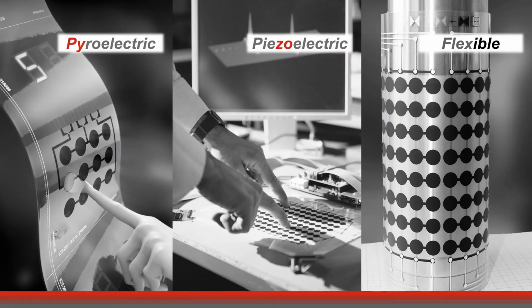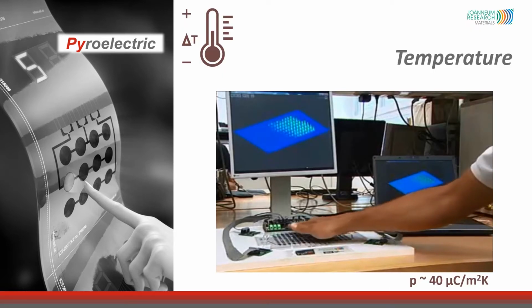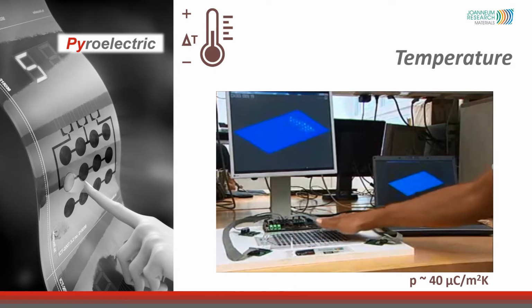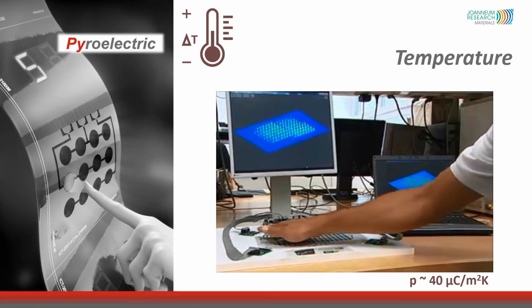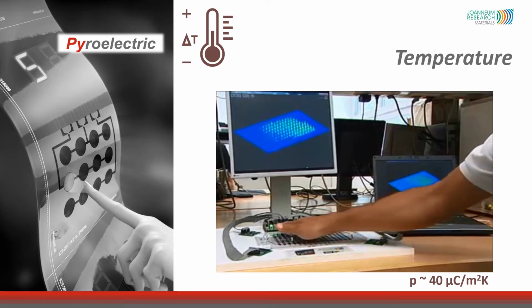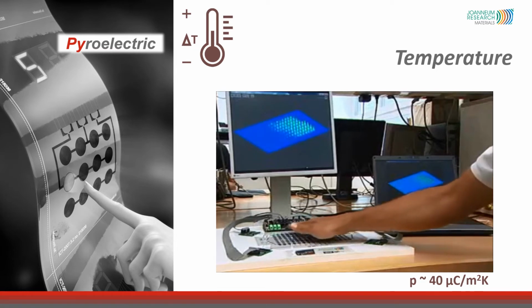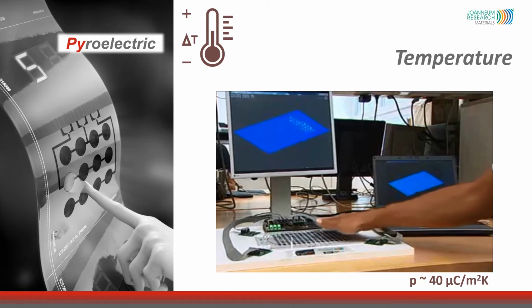The brand name Pyzoflex illustrates the essential properties of our technology, namely pyroelectricity, piezoelectricity, and flexibility. First we have pyroelectricity, which is the sensitivity of PVDF-TrFE to temperature variations, induced, for instance, as shown here, by body radiation. It is parameterized by the pyroelectric coefficient, which is 40 microcoulomb per square meter Kelvin in our printed sensors.